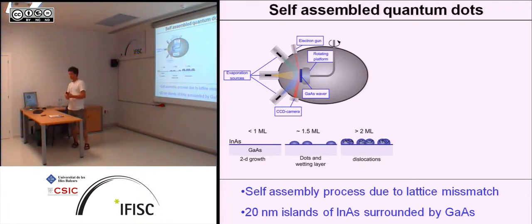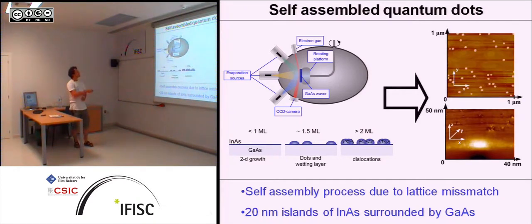It's a bit like if you look at a frying pan of Teflon and you put water on it, you see these little droplets forming. So it's a similar effect to that. If you go above the critical thickness of such a layer, you have these single or small droplets forming on top of the gallium arsenide. The ones you want are in this area. If you go to big quantum dots, then you have dislocations. And finally, you will end up with something like this.